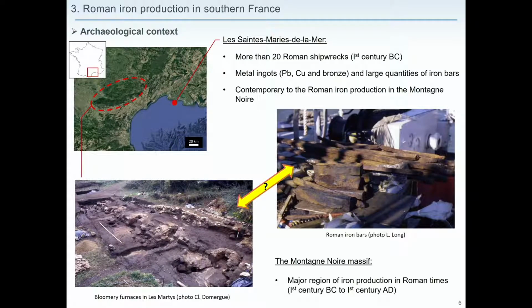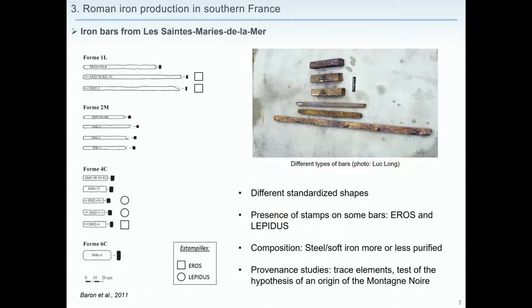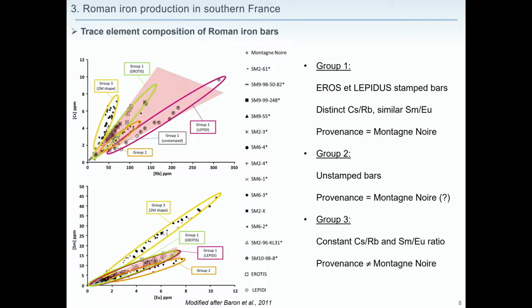So we test the hypothesis of a provenance from the Montagne Noire for this bar found near Les Saintes-Maries-de-la-Mer. This bar could have different shapes. Some show stamps, which correspond in fact to different workshops of iron bar production. Their composition varies between steel and soft iron. And a previous study tried to test the hypothesis of an origin from the Montagne Noire using trace element analysis and slag inclusions. So here are the results of this study.